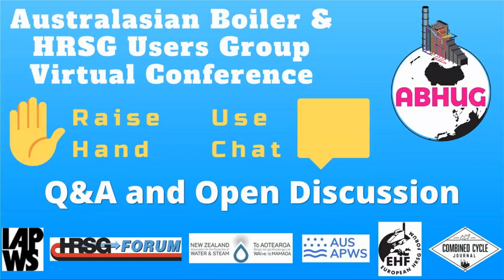Anyway, it's to try to take a little bit more proactive approach instead of waiting for this oxide to catch you up, because as you probably know, there are oxidation limits, and some of your temperatures there are very close to them. You have an oxidation limit for T22 of 580 degrees C, and for T91 of 605, and they're very close to that. And when you get the oxide growing very thick on the inside, every time the oxide grows by 25 microns, it increases the tube temperature by 2 degrees. And so there are things that you can do, that you don't need to wait until you get into the situation that you showed.